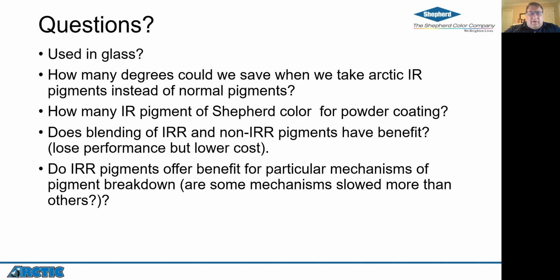Do infrared reflective pigments offer benefits for particular mechanisms of pigment breakdown, or are some mechanisms slowed more than others? All of these, as I mentioned, are complex inorganic colored pigments. They're ceramic in nature, and the infrared reflective properties are inherent with the pigments. As CICPs, as this family in general, these have excellent durability. We did mention earlier that if you do keep things cooler, there theoretically should be less degradation of the overall system, but it depends on the pigment chemistry. So that's the pigments themselves, and the resins in there should behave similar to all the other CICPs.